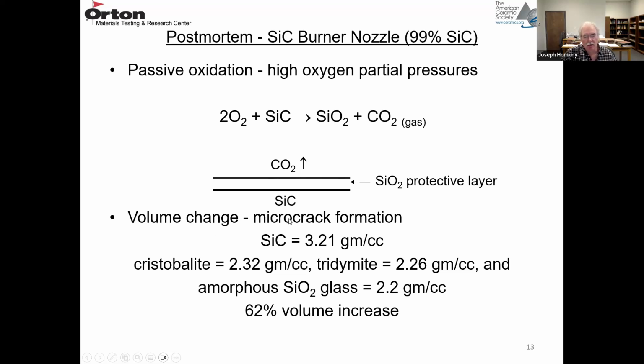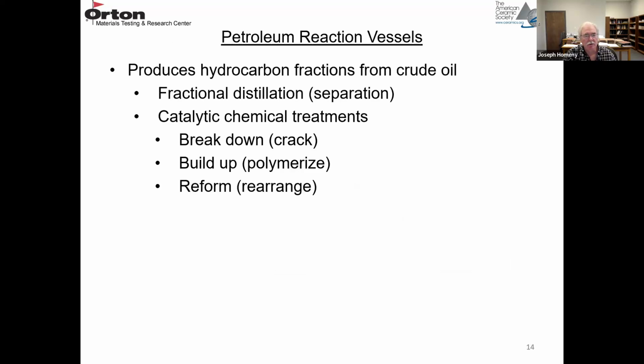But there's a big volume change here. Silicon carbide is 3.21 grams per cubic centimeter. And the oxidized products are a lot lighter. Cristobalite is 2.32, tridymite is 2.26, and amorphous silica-based glass is about 2.2. So there's a large volume increase when this material oxidizes, and that's why we have all those microcracks from all the stresses that are formed when this volume change takes place. So that was a silicon carbide burner nozzle.